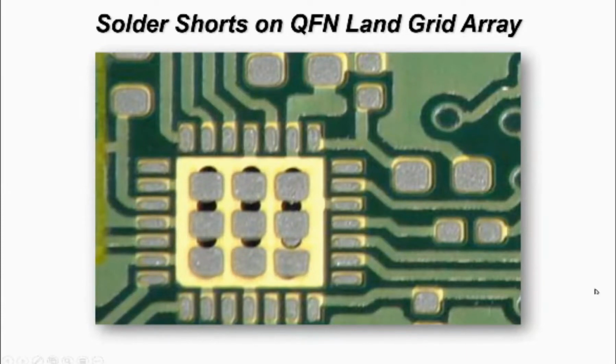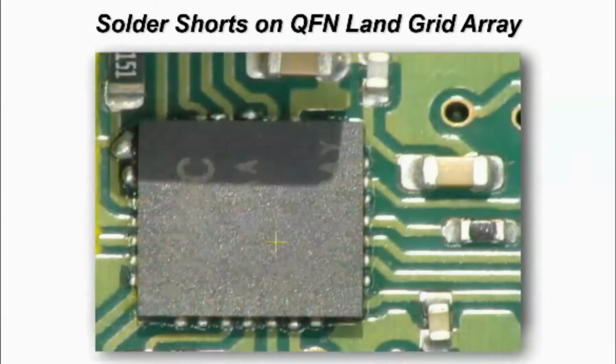Again, we've got a standard pattern. You can see multiple deposits of solder paste on the center pad. These vias are actually filled with solder mask. But unfortunately, when you actually place and then reflow, what you're getting is blowback. So the volatile material can't escape at all.